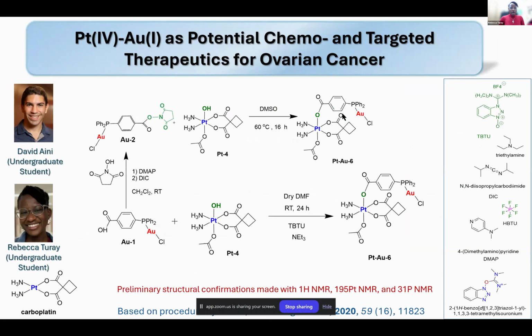We have multiple methods for synthesizing, but our primary one begins with the gold-1 compound, where we used our platinum-4. We ran the reaction in dry DMF at room temperature for 24 hours using coupling reagents TBTU and triethylamine to obtain our PtAu6. That's one method. But we also saw that we could synthesize it using an activated ester form of the gold-2 compound, along with the platinum-4 in DMSO for 16 hours at 60 degrees, and we can also obtain a platinum-4 gold-1 heterometallic compound. We got better results using the DMF and coupling reagents, so we continued further with that.